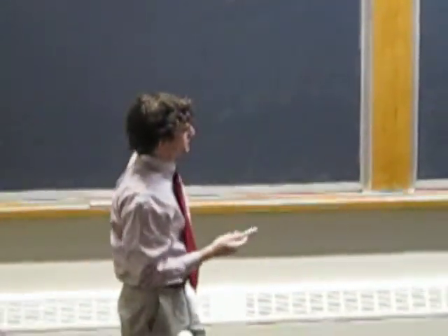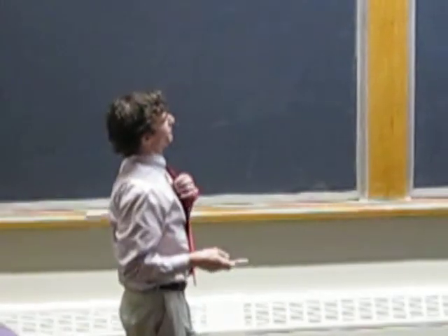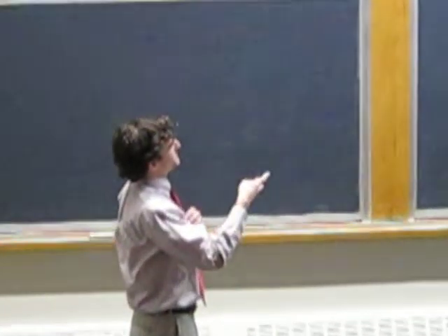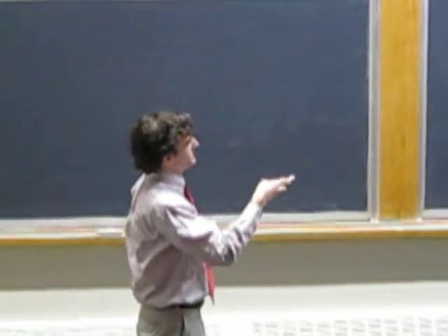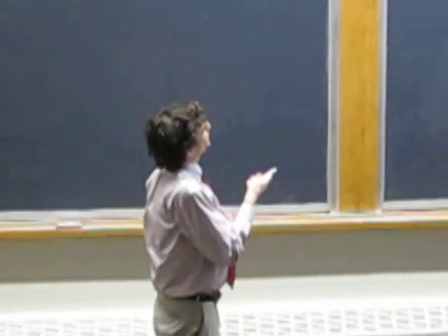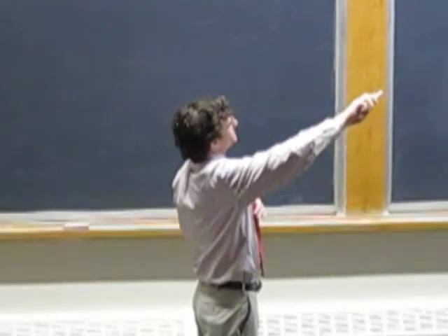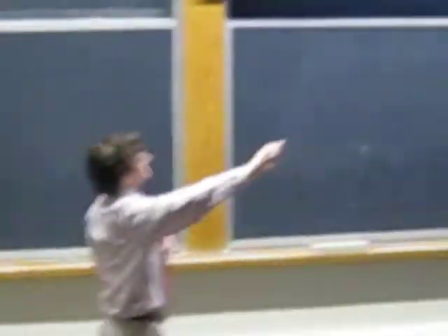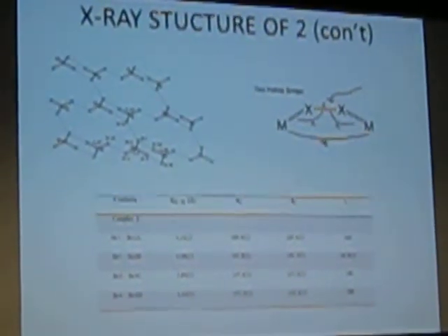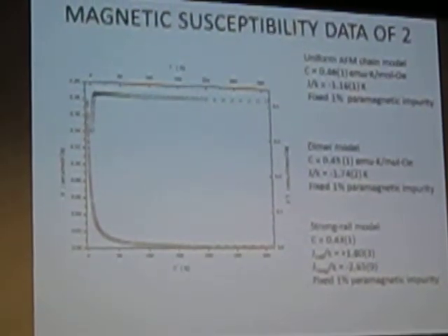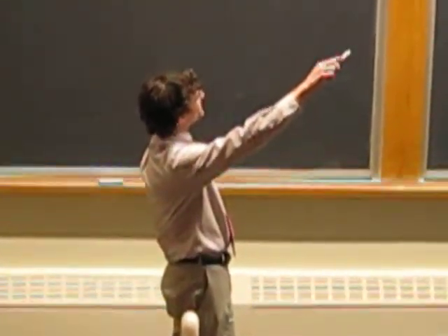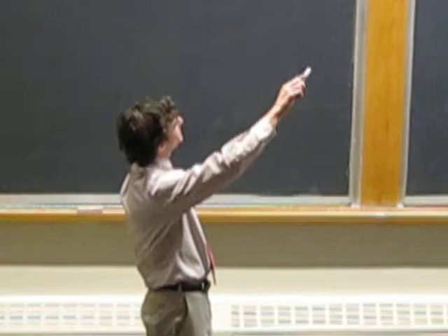At 3.84 angstroms, we've had materials that have very moderate to strong exchanges at these distances, and the dihedral angles are ideal. The only thing that is not ideal is the angles between the atoms, and they're less than ideal. But other than that, you would expect, or we expected, to have moderate exchange or strong exchange across these metal centers. And what does the data tell us? Well, the variable temperature magnetic susceptibility data is rather disappointing. As I've plotted here also the chi-T plot on the same graph.